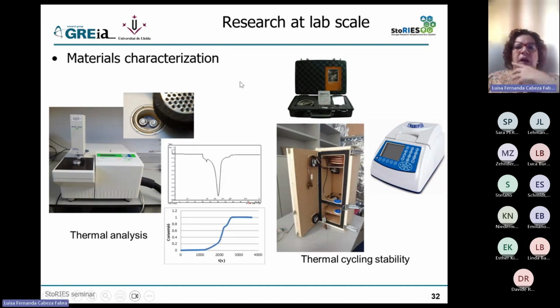In the characterization, as you can imagine, we work a lot with thermal analysis. This is an image of our DSC. There are different DSCs that can be used for characterization of thermal storage materials, not only this one, but this is one of them that we use. And we work in developing the best technology or methodology to do this characterization. But this equipment that you see in this photo, which is kind of a box, was homemade equipment that we developed also a few years ago. And the idea here was that when we were working with our calorimeter, the calorimeter we use is this type of calorimeters that is a heat flux calorimeter, and it uses only milligrams of material.